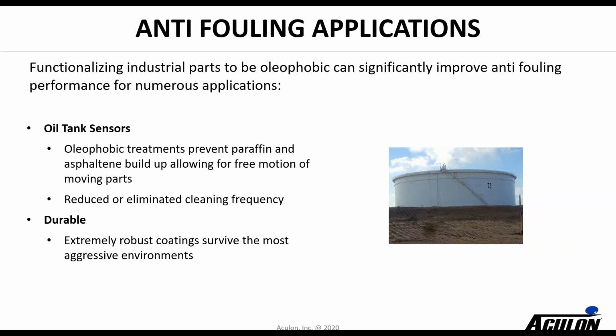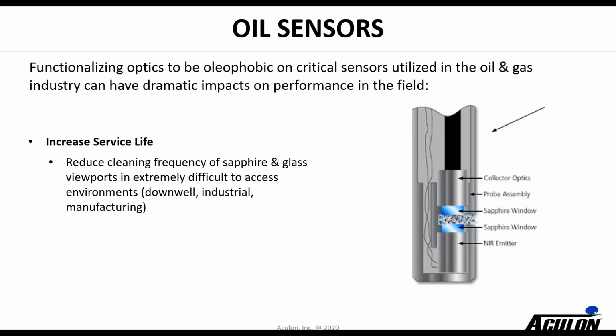Well, if you treat the sensor and the stainless steel tube before it goes into the tank, you can go from a maintenance schedule of every 3 to 6 months draining and cleaning out that tank to 4 or 5 years, where you now don't have that buildup. So it's an extremely aggressive environment, crude oil, and obviously one where you need durability.